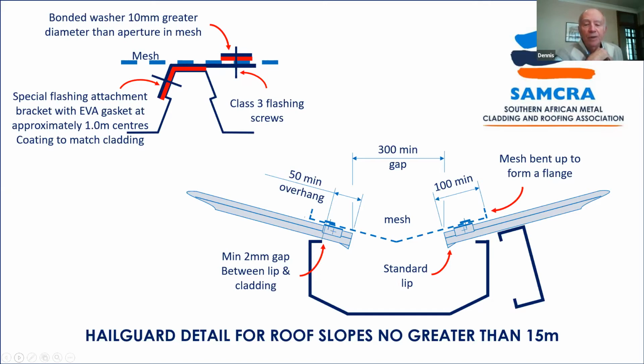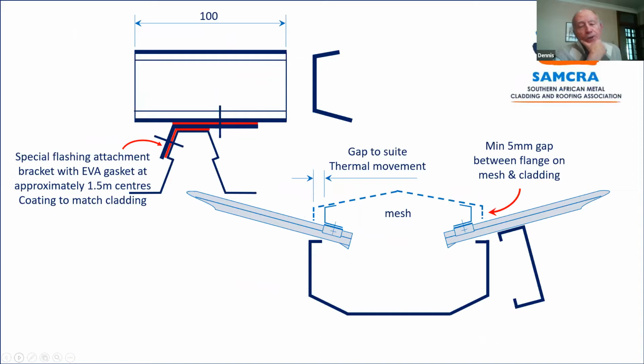And then if we go on to the next one, this is an alternative to that. And what you do is you have these little channel cuttings that you attach to the rib of the cladding. And you can have them at every 1.5 meters, up to 1.8 meters apart, depending on what mesh you're using. And then you bend your mesh to look very much like a ridge flash. And you just let it float on top of the channels, and the sheets can move underneath quite independently without any risk of interference with the thermal movement and the Hailguard or the Hailguard supports. Right, next one.